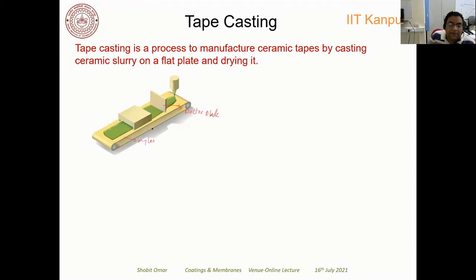Okay, so in tape casting you can make free-standing membranes, and also you can make coatings on a particular substrate, right? So both are possible using the tape casting technique. What happens is that this mylar rotates, and it normally is a plastic material, and the coating is done on the mylar. You pour your liquid on this, and this liquid passes through the gap between the doctor blade and the mylar, and you will have a uniform coating on top of the mylar.